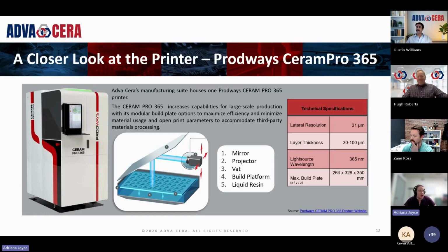Yeah, so we are limited by wall thickness, sure, but the largest external dimensions of the part that are possible with the printers that we have is 264 by 328 millimeters in the green state. So depending on whether you're looking for an alumina part or an aluminum nitride part or silica part, those are going to have slightly different shrinkages. So take 20% off of that, and I admit I can't do that math in my head, but the largest build plate that we have is on the Prodways with that modular build plate. So 264 by 328 by 350 times minus about 20%, you can average. Assuming that your wall thickness is within spec, and that's just your bounding box.